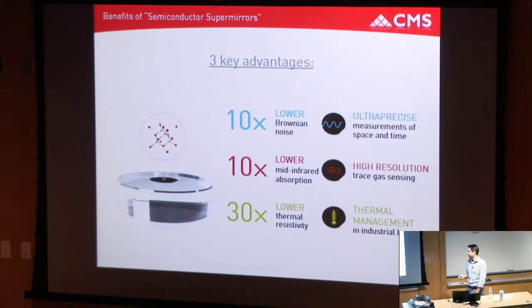maybe some new physics. It also turns out that these materials, gallium arsenide-based materials, have a very wide transparency window. We are precluded from working in the visible because the band gap of gallium arsenide is about 870 nanometers at room temperature, but the transparency window extends to 12 microns. So there's the ability to make extremely low-loss mid-infrared optics with these systems, and typically you can get good ion beam sputtered optics in the visible and near IR, but they cut off at about 2 microns. And so going beyond and really getting these PPM level of losses is quite challenging with existing coating technologies. So this is potentially one direction to get there.